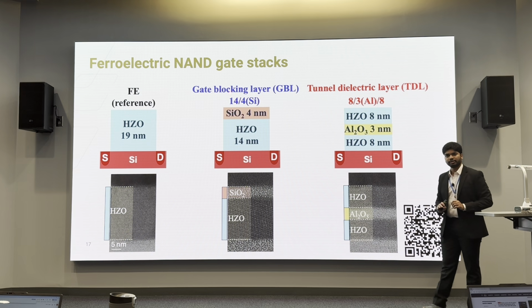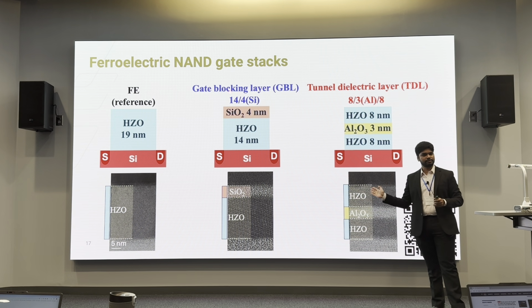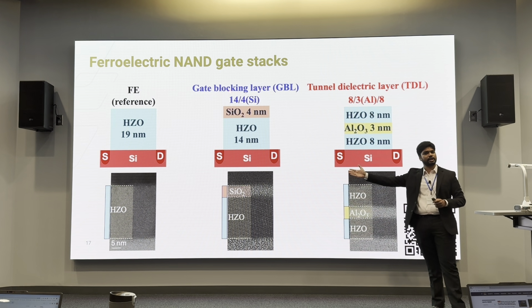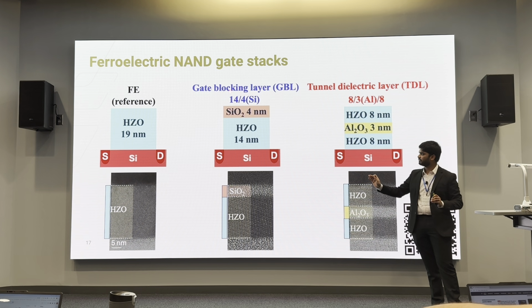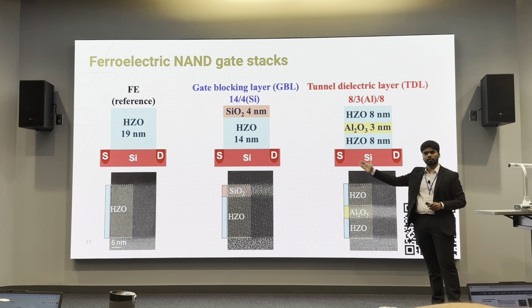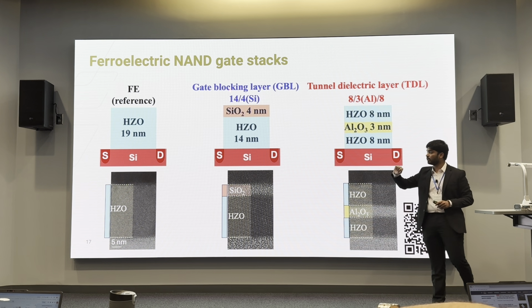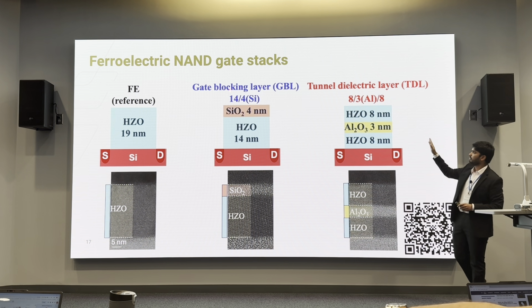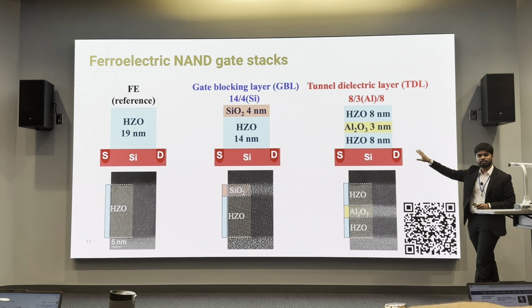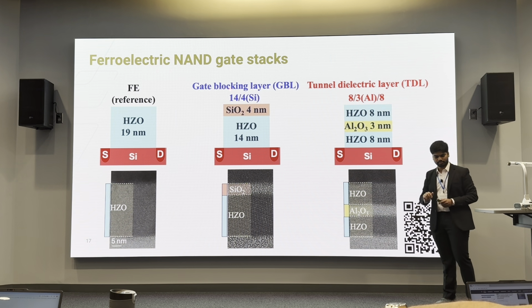So in order to study retention, we started out with 3 different gate stacks. One is the standard 19 nanometer gate stack, plain old heterogeneous FEFET. Then we used a 14-4 silicon dioxide gate blocking layer, with a 4 nanometer silicon dioxide gate blocking layer at the top. Then we have our tunnel dielectric layer, where we have a 3 nanometer aluminum oxide layer in the middle.